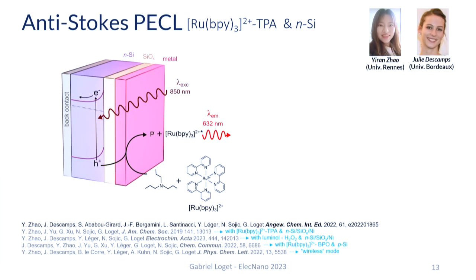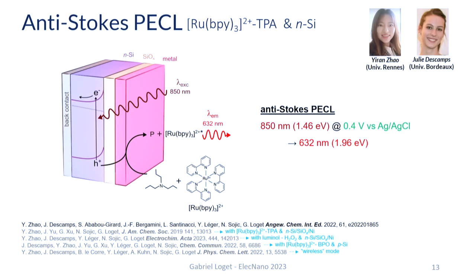Here you can see a scheme of our system. We have our silicon photoanode with the two thin protection layers. We are going to use front-side illumination, which means that we irradiate through the electrolyte and the protection layers. The protection layer is very thin, so the near-IR light can generate photo electron-hole pairs. The photo-generated holes are going to be collected at the metal thin film and are going to trigger the ECL reaction, which will lead to the formation of visible light. So here, if this works, we should have an anti-Stokes PECL process where near-infrared light, low-energy light, is converted into visible light with a higher energy.